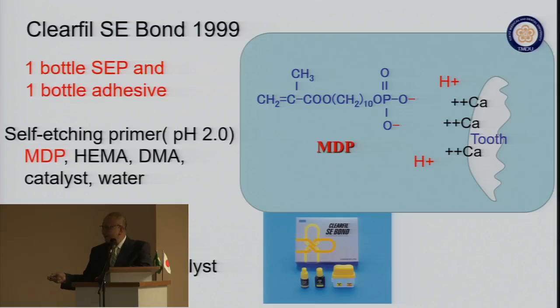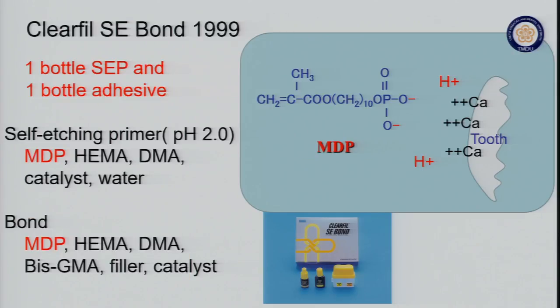Okay, let's go back to the two-step self-etching. After the application of self-etching primer, we remove the water from the primer. Then we apply the bonding resin without water, without water. Again, it contains MDP, HEMA, dimethacrylate, Bis-GMA, and filler, and catalyst. That's why we can create a very strong bond layer.